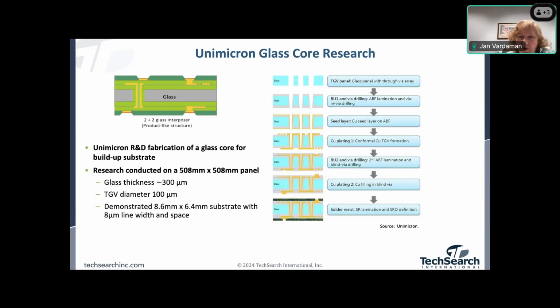So Unimicron has been working on the research for glass core for a very long time. Their initial research has been done on a 508 by 508 panel, glass thickness of around 300 microns, TGV diameter of around 100 microns, and they've demonstrated an 8.6 millimeter by 6.4 millimeter substrate with 8 micron line and spaces. The key here is to bring up the yields in this process and make sure you can do this without the glass cracking. So again, do it with multiple buildup layers. Next slide, please.